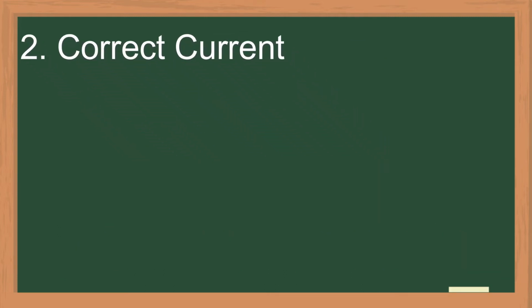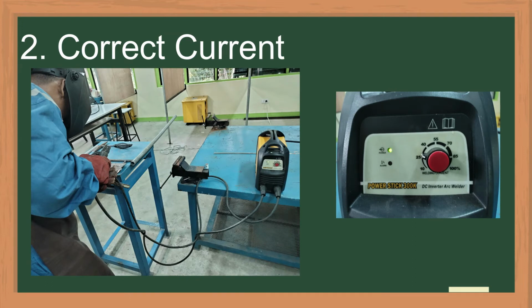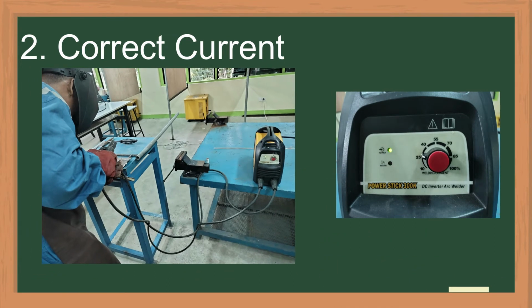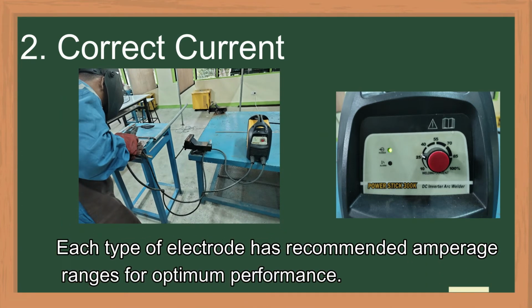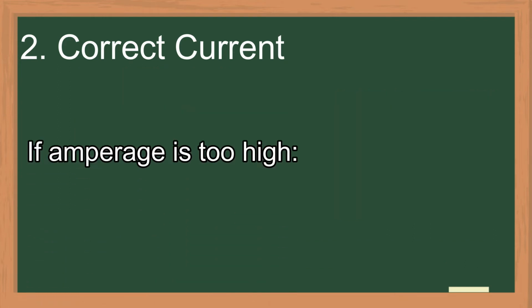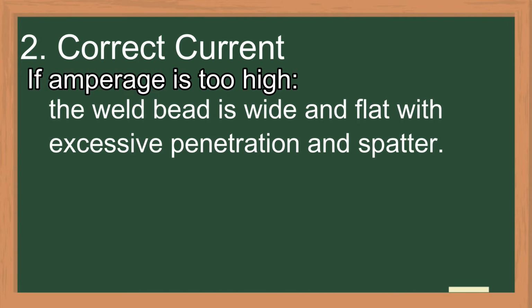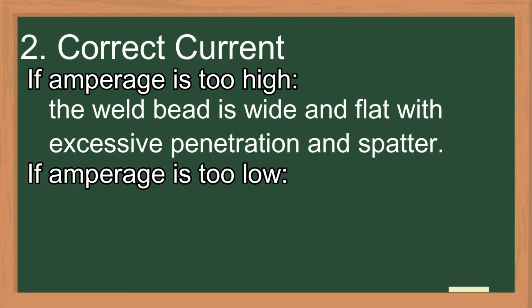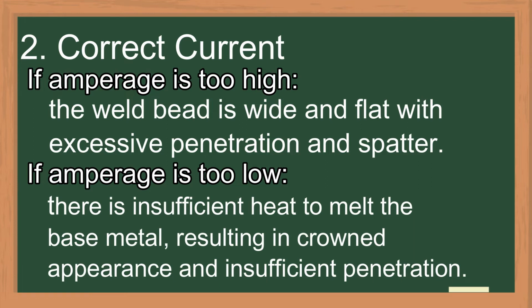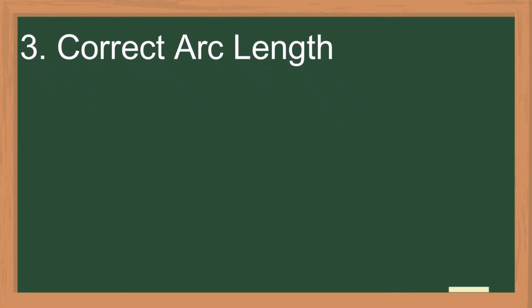Number 2. Correct current. Remember that current can be measured in amperes. Each type of electrode has recommended amperage ranges for optimum performance. If amperage is too high, the weld bead is wide and flat with excessive penetration and spatter. If amperage is too low, there is insufficient heat to melt the base metal, resulting in a crowned appearance and insufficient penetration.